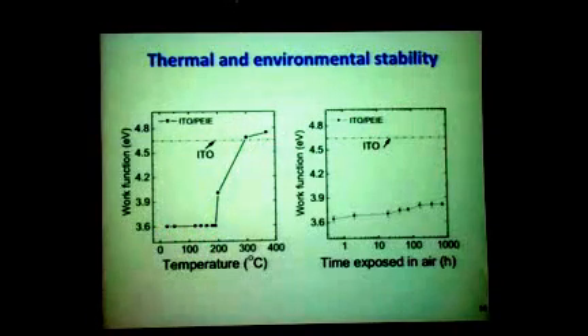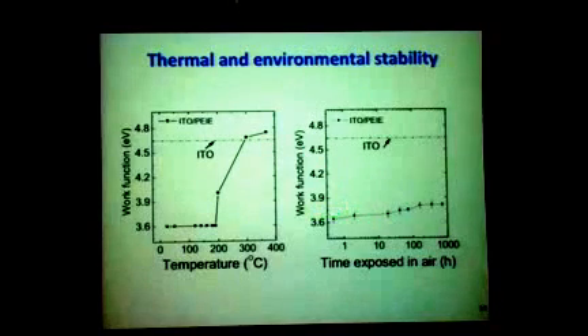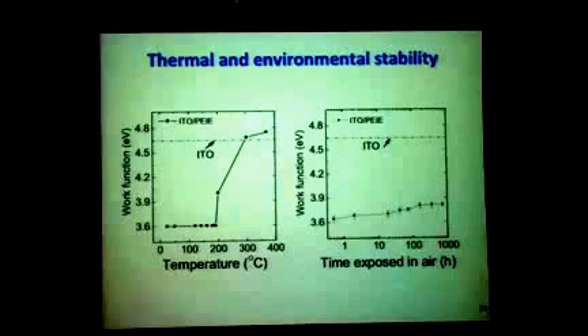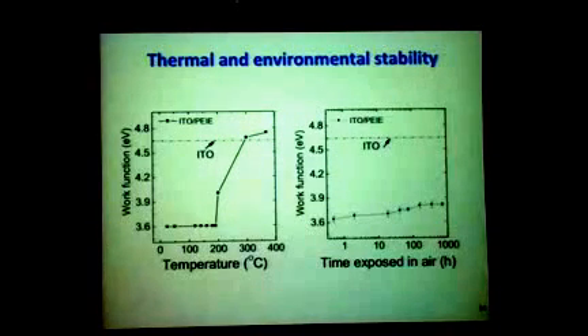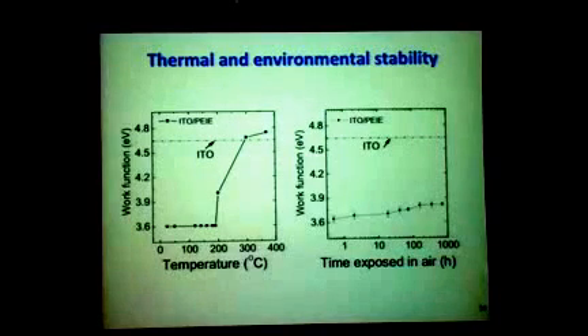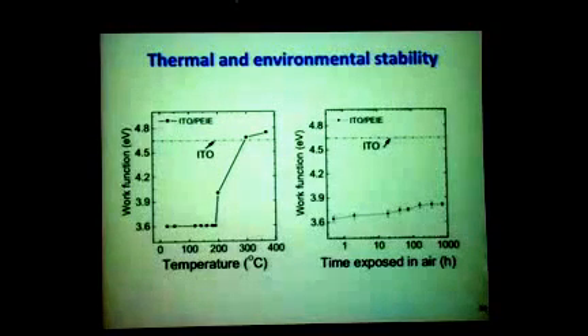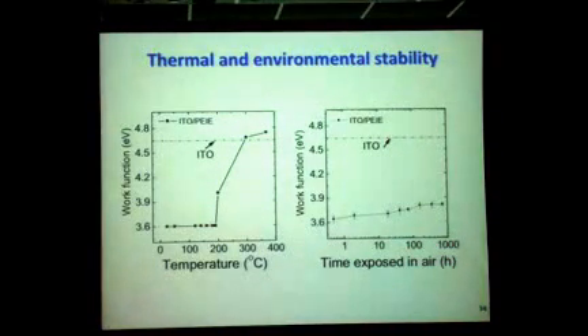So these PEIE materials are sufficiently stable. But really what's remarkable and game-changing about these materials is now you have electrodes with a work function that's in the range of what you can usually get with calcium, but it's air stable. Now that changes everything, because now you can manufacture these devices in air rather than in glove boxes or in vacuum. The packaging is going to be much simpler, so you save a lot in cost. It's really disruptive in terms of the improvements it has on solar cells.